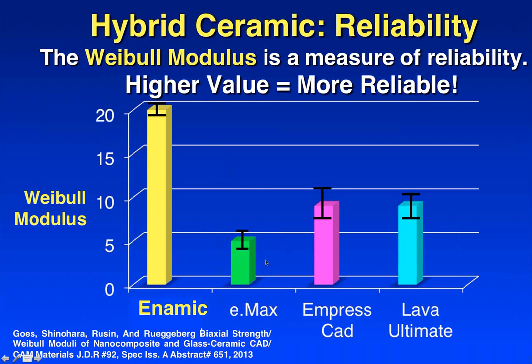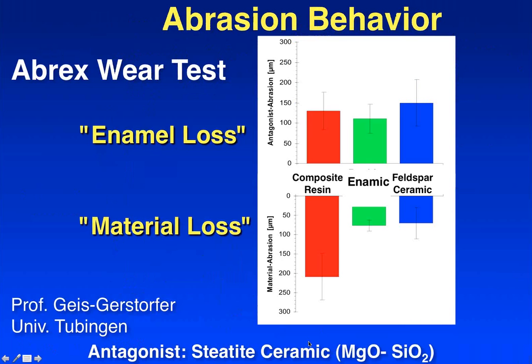E.max is under 5, so you have a very wide range of failure for that material. Empress CAD and Lava Ultimate are also under 10, which means you get a fairly wide spread of failures for that material; you don't really have a highly reliable, reproducible material. Everybody was surprised at this value too. It was another surprising thing.